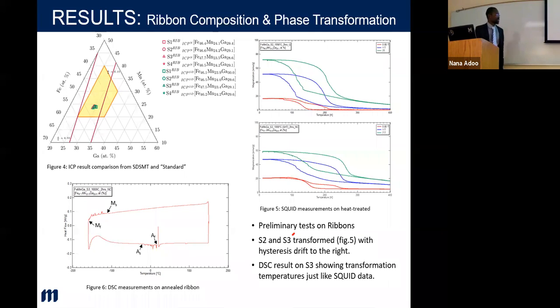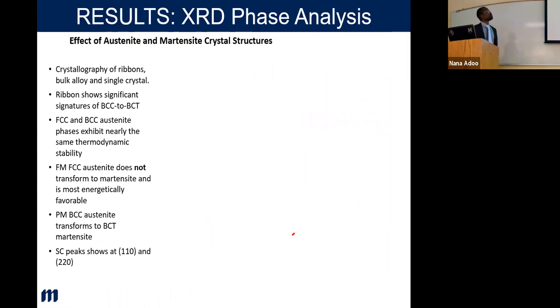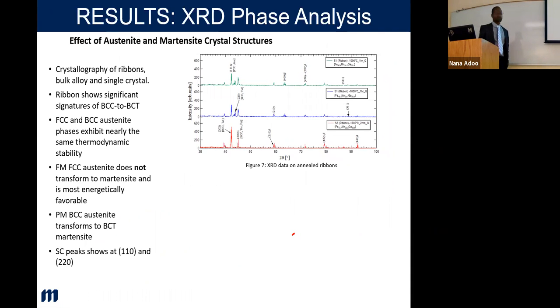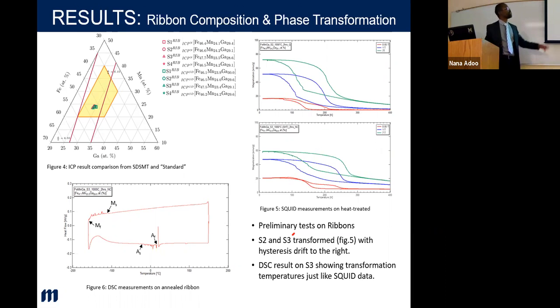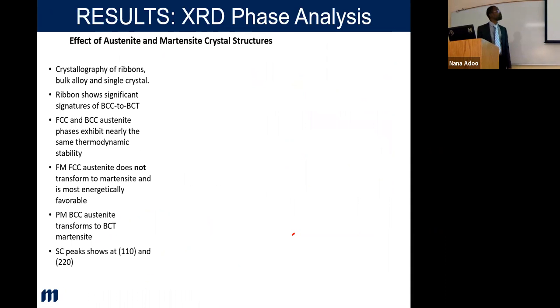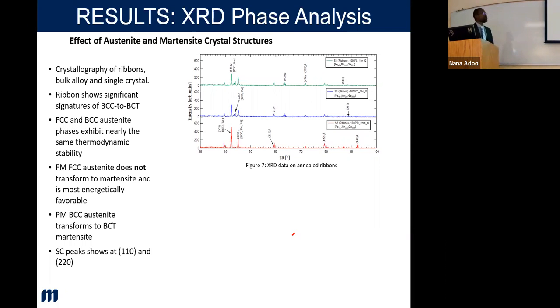And so DSC temperatures actually match the SQUID and also confirmed the transformation ranges that we were looking at. So to confirm the crystals that were actually being generated within these regions, the austenite or the martensite regions, I looked at XRD analysis, and XRD will show you which kind of crystals are forming, and the technique actually uses X-rays. By subjecting X-rays to it and looking at the crystal reflections, you are able to know which ones, by their structure factor, match either an FCC or a BCC crystal phase. And looking at these for the ribbons, I could see some BCC and FCC mixtures in the transformation.